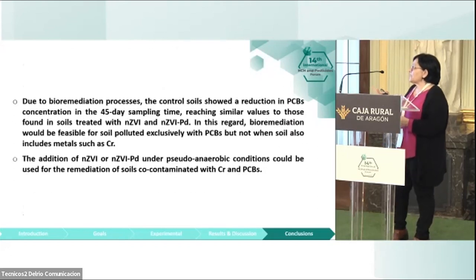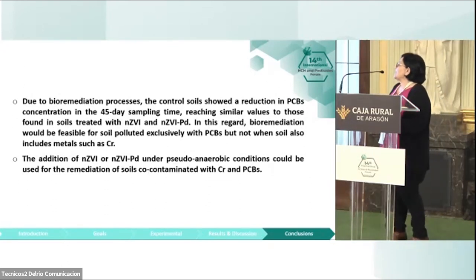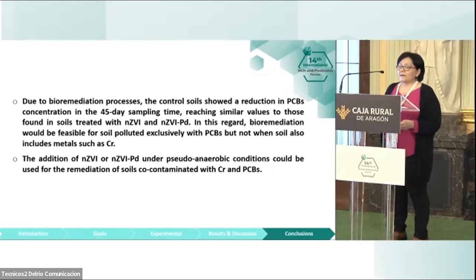The bioremediation process will be useful for the soil. We can obtain the same results with nanoparticles, but the problem is that the bioremediation process won't be able to reduce the chromium, and therefore the chromium concentration would still be there in the soil. And this is the problem with a soil mixed with different contaminants, because it is more difficult to look for